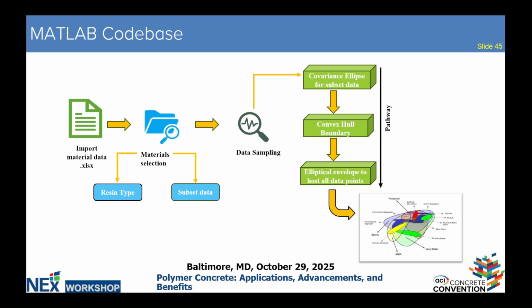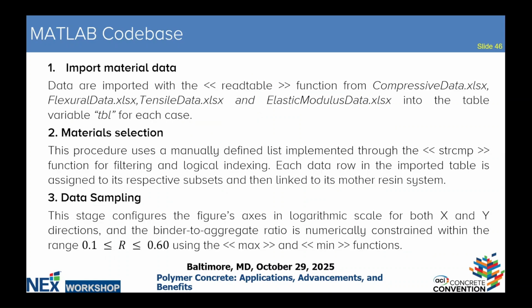binder to aggregate ratio of 0.1 to 0.6, as we normally build within those ranges. And we went through the covariance ellipse for subset data, convex hull boundaries, and the elliptical envelope to finally get the Ashby chart you see beneath there. So I'll be going through each of them. As I said, I segregated the data into compressive data, flexural data, tensile data, and elastic modulus data, as I initially said.